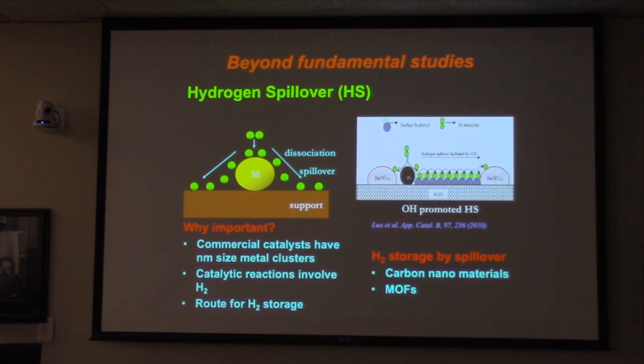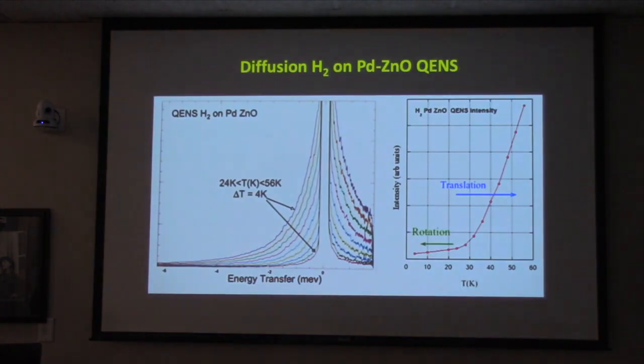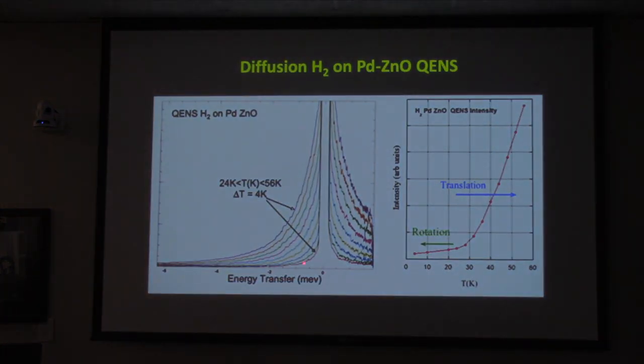And what happens, and I knew nothing about this when I first started, it turns out that the hydrogen becomes active and it moves along the surface and then reacts with some other molecule or some other site. And neutrons are good for that because, as I told you, you could do things like quasi-elastic scattering. This is that quasi-elastic scattering. And as you increase the temperature, it turns out the molecules are more and more both rotationally and translationally moving.